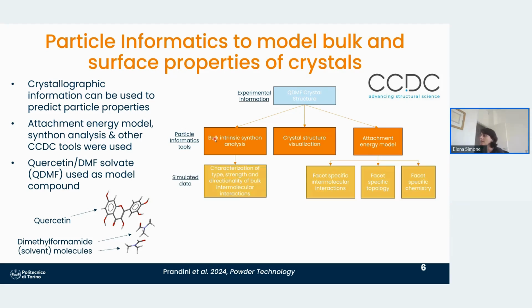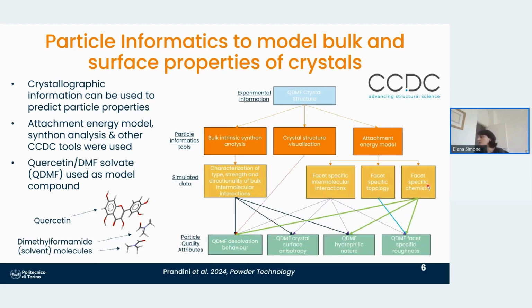So with these particle informatics tools, the type of data that we get is, again, a list of intermolecular interactions within the bulk crystal lattice, where we can separate and rank them based on their type. So whether it's a hydrogen bond or a non-polar interaction, then we can measure the strength and the directionality. The directionality is then used, through the attachment energy model, to calculate facet-specific intermolecular interactions, so how a specific facet is growing, to calculate the topology, so basically to get atomic roughness maps of the facets, and then to understand the facet-specific chemistry, so what parts of the molecules characterize each facet.